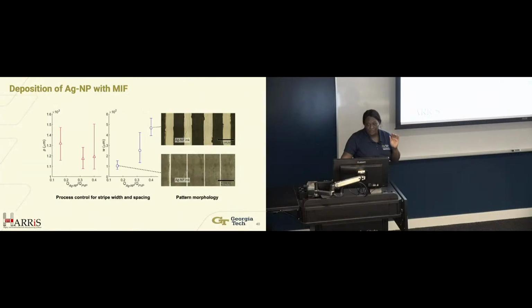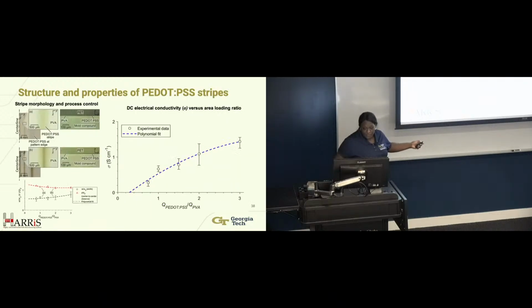In terms of the mixing at the interface, depending upon the materials and their miscibility, you may get more or less mixing or spreading at the interface. So you see with the silver nanoparticles and the PVP, there's little to no mixing. But with the PEDOT:PSS, you can see it a lot more. I don't know if you can see that. I can see it pretty clearly up here, but this is more manila than this region here. So this is the PVA, this is the mixed boundary, and this is the dense PEDOT:PSS. The spreading of this region is contingent upon the rate at which we're processing and that standoff height, the gap. So it's material dependent. Oh, yes.